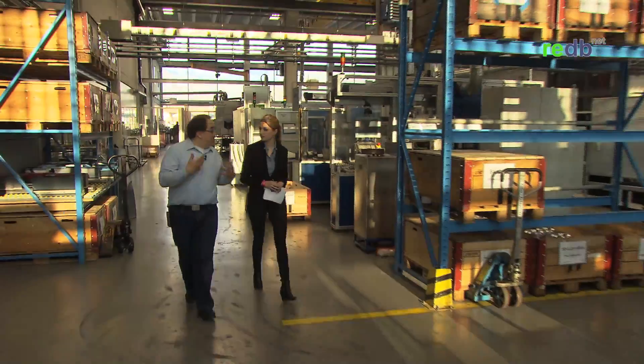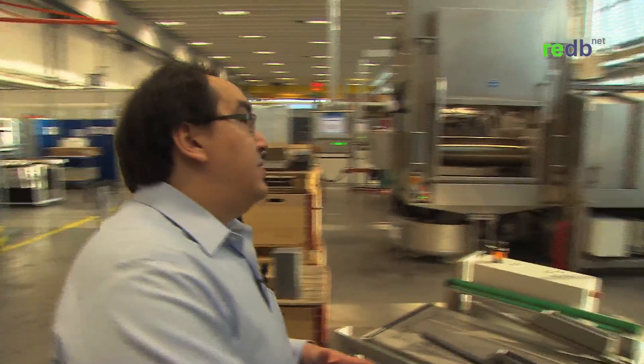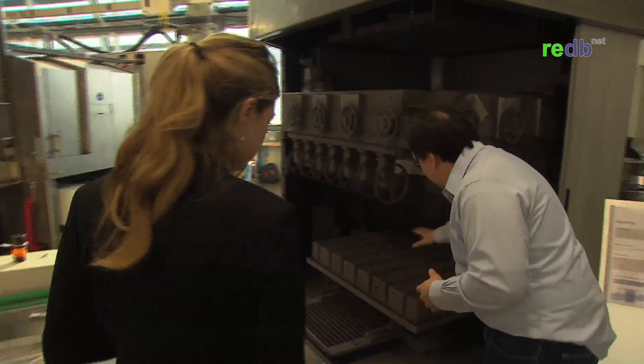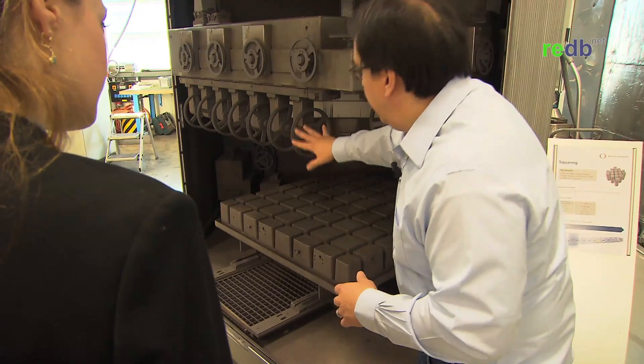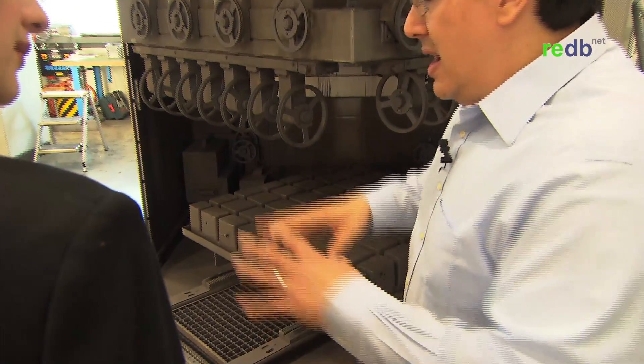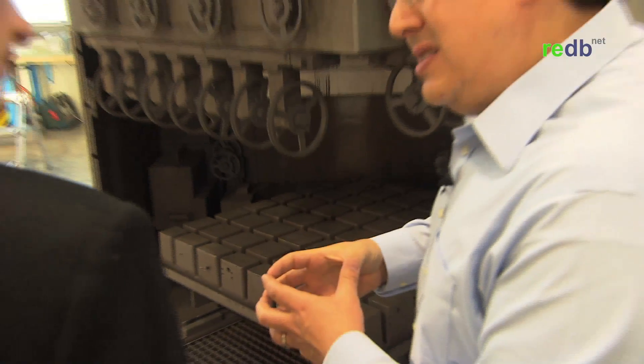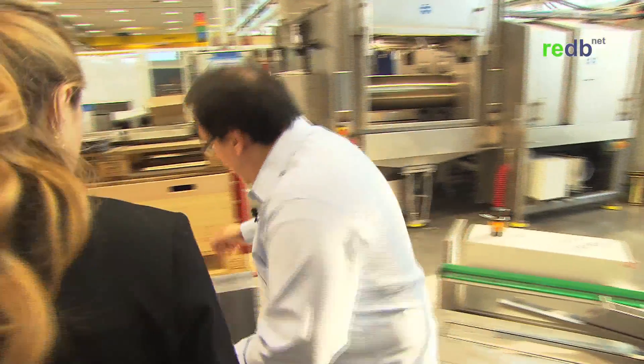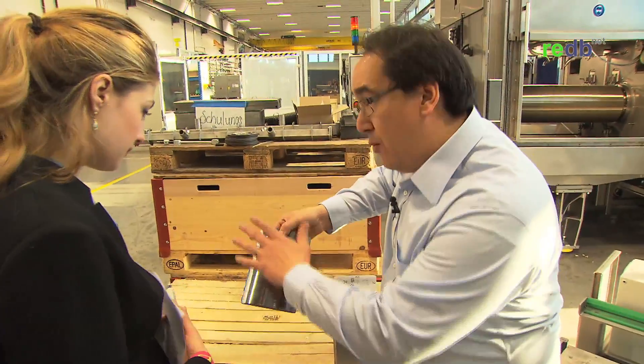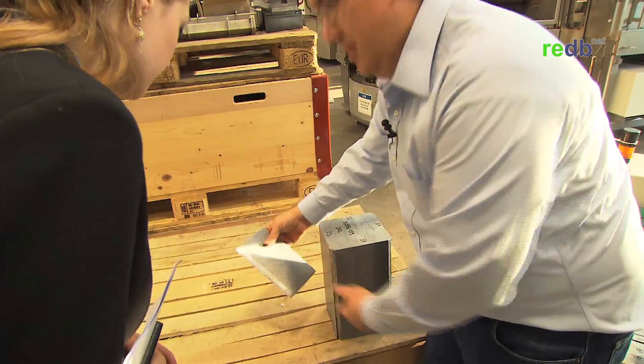We're walking over to what we call the Brickmaster. The Brickmaster is the tool that does the squaring for us. This round ingot is loaded into the machine. Inside, each square place will have an ingot laid in it. Up here we have a grid of diamond wire. This grid of diamond wire will make a square inside there. This is what we call the cutting yoke — it comes down and cuts the pieces off. The wire comes on all four sides and cuts off the sides, so we go from round to square.